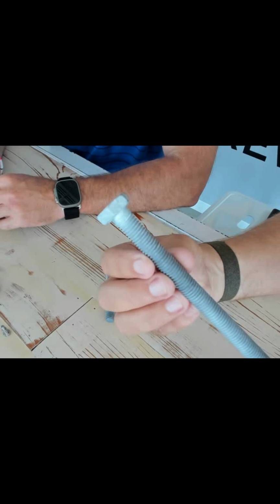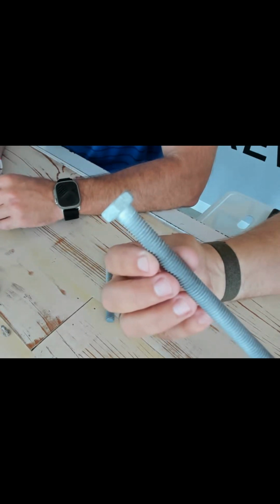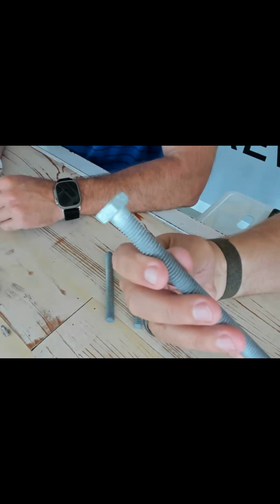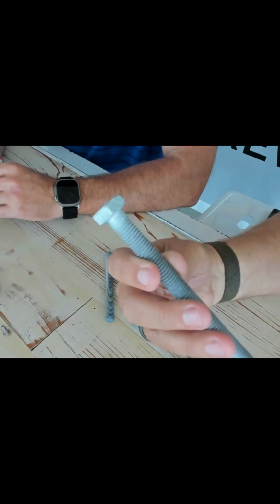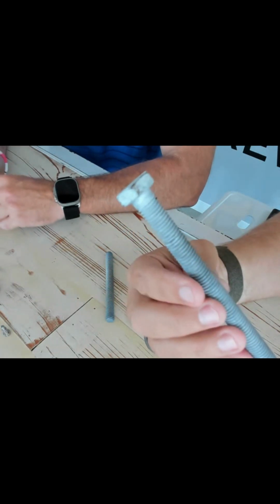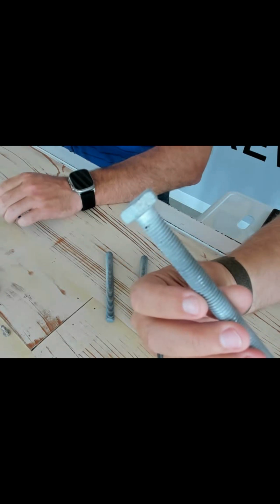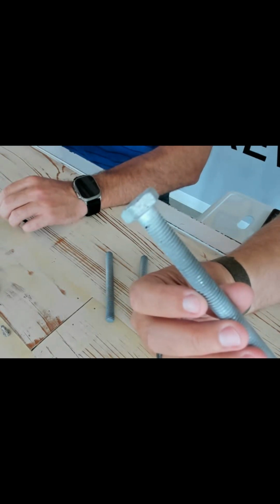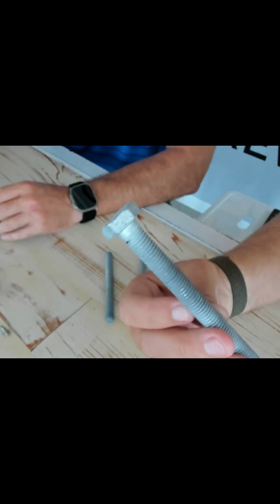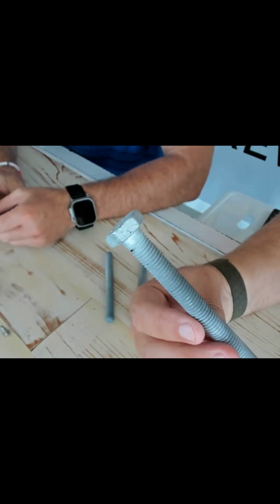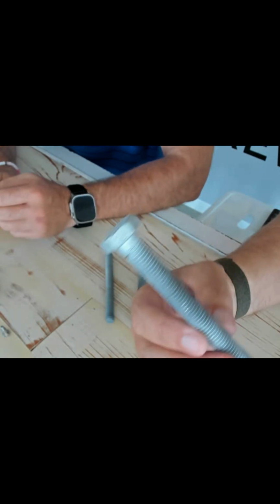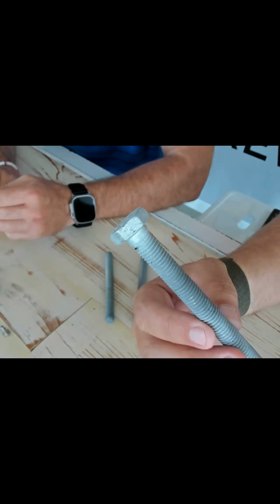So to ensure that nuts fit, they'll be brought in after the hot dip process, and then they'll be overtapped at that point. Yeah, and generally where you're allowing 10 thousandths over on a PTFE coating, on hot dip galvanized you're generally overtapping at 20 thousandths, so twice as much to allow for that coating because it's so thick and because it's so inconsistent.